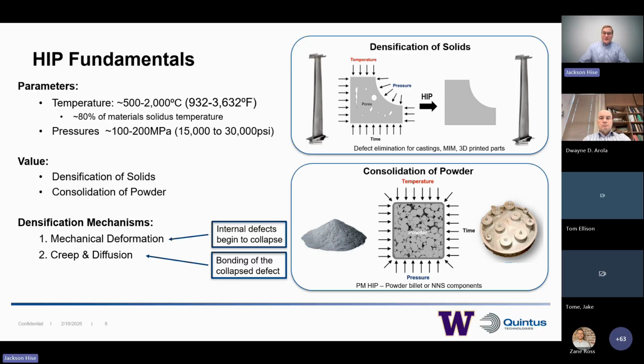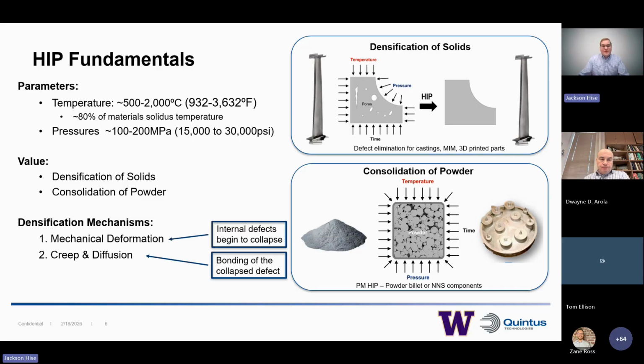This is significant because it rivals traditional forging, except that the cycle time, the process time, the manufacturing time is significantly decreased compared to those forging operations. If we want to think about just the quick material science, I know Dwayne will get into more of this. Densification mechanisms first go through mechanical deformation, where we have the defects collapsing because of this applied pressure. And then over time, over our hold, we have creep and diffusion, where we're seeing that these collapsed defects are bonding.